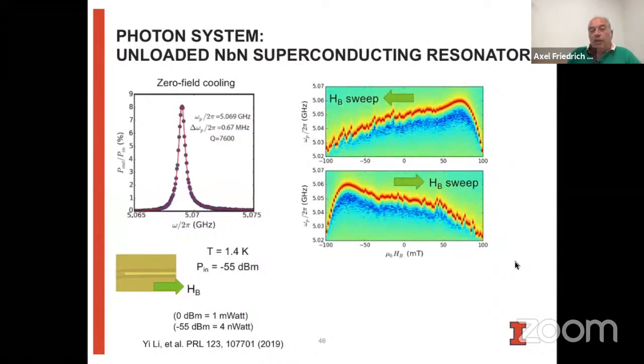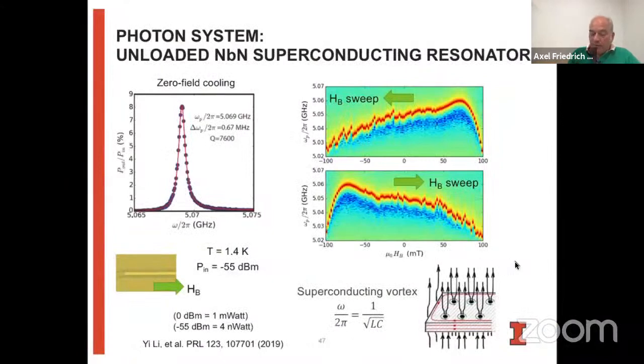Now, we wanted to look then at the magnetic field dependence of this resonator. And what we see is that as we sweep the magnetic field, in the lower picture we sweep the magnetic field from left to right. In the upper picture, we sweep it from right to left, from positive to negative. We see that the resonance frequency of this resonator does depend slightly on the field. And what happens is that as we sweep the field, we do introduce vortices in the superconductor, and the vortices give rise to additional kinetic inductance, which thereby decreases the resonance frequency of the resonator that we have. And we see this behavior as hysteretic, but this is our baseline for when we look at a system that has a magnetic component integrated into it as well.